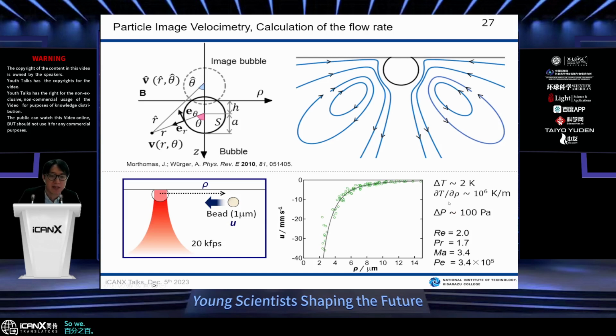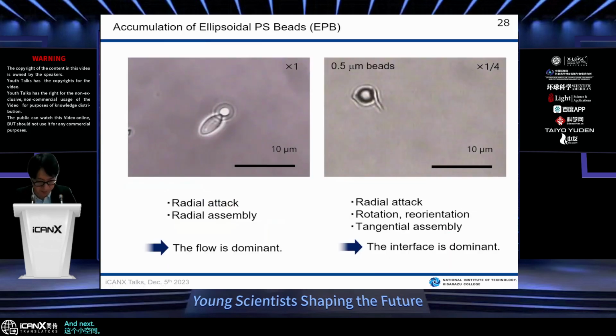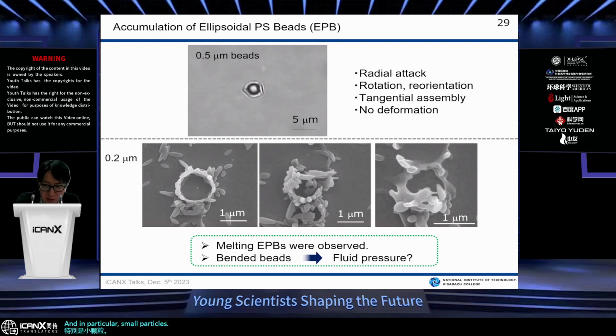So we succeeded to characterize this small space. And next, I tried to monitor the behavior of ellipsoidal polystyrene beads, as shown here. The bubble attracts the particles, and the larger particles accumulate radially, like this one. In contrast, smaller particles show tangential accumulation. So it's different, and in particular, small particles show unique properties.